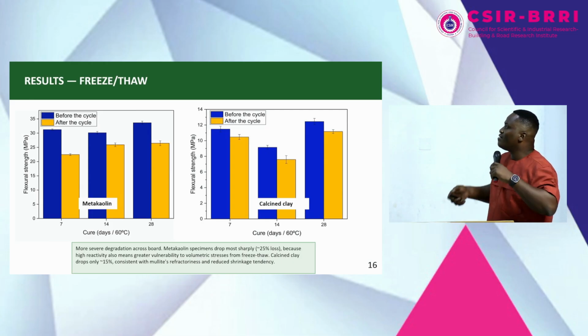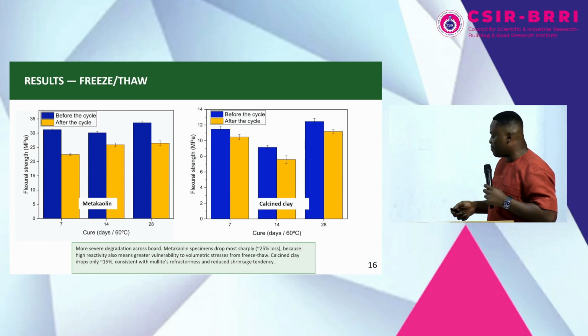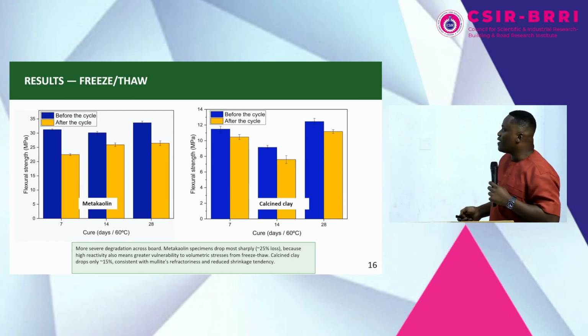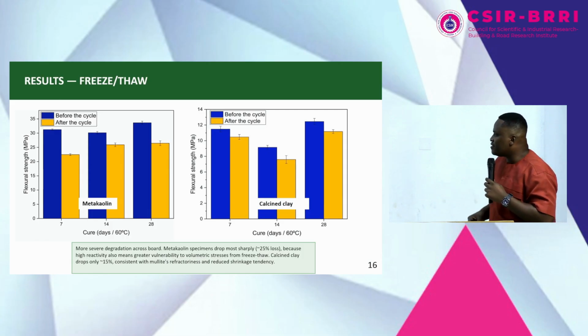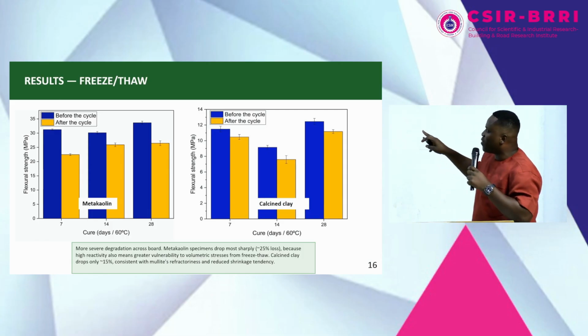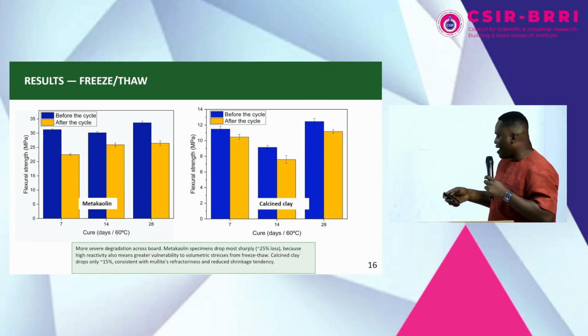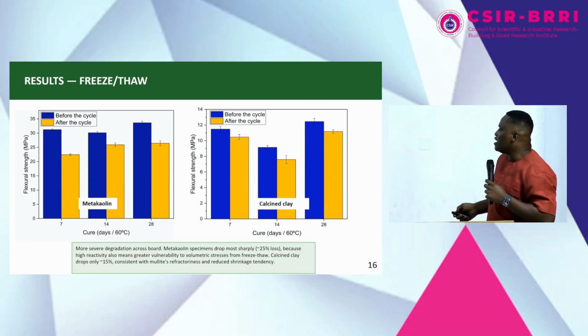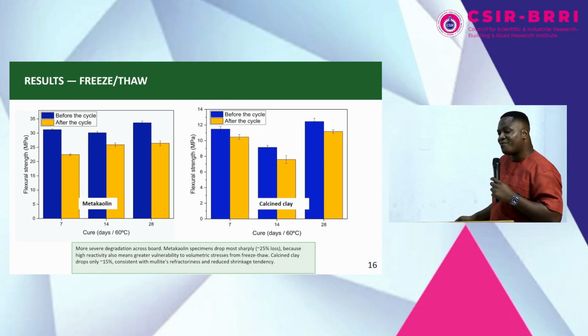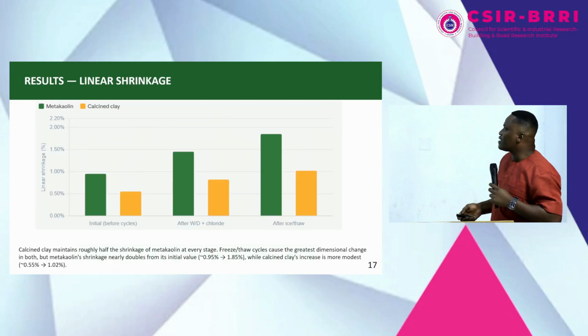And so this is the freeze and thaw, as I explained. Think of it as within winter and within summer, how the material will fare. But let's consider just the 28 days. You realize that similarly, more severe degradation comes across the board. All of them are suffering degradation. However, the metakaolin is losing about 25% strength after the freeze and thaw cycle, and the calcined clay is losing just about 15% of its strength after the freeze and thaw cycle.